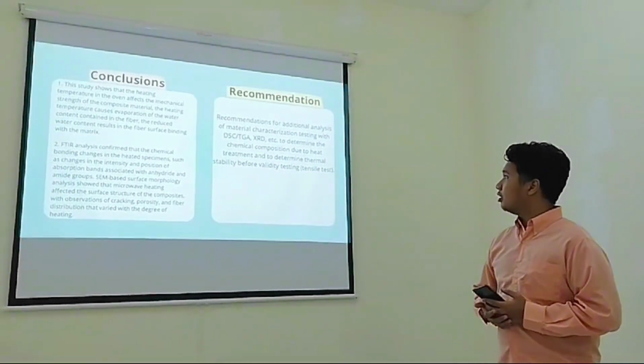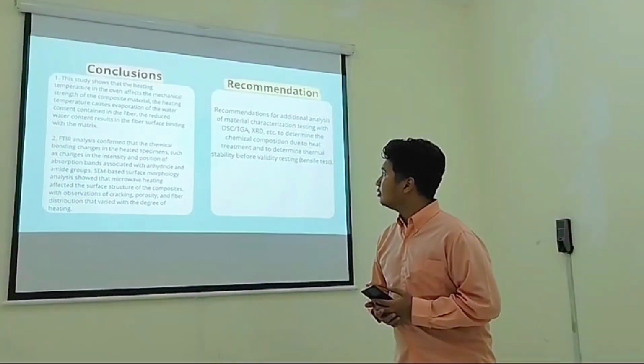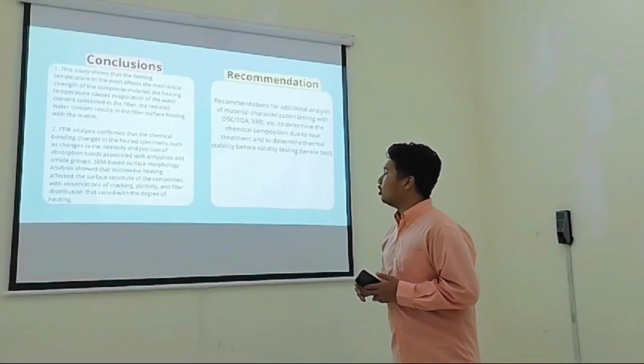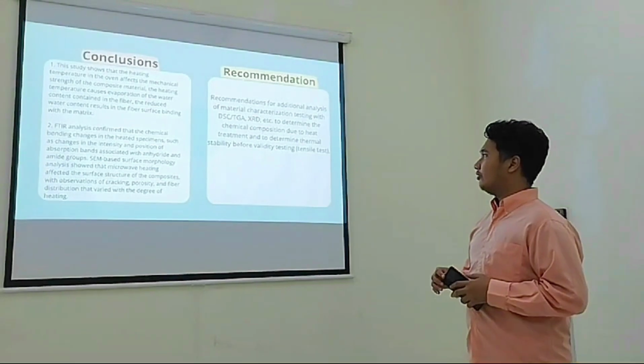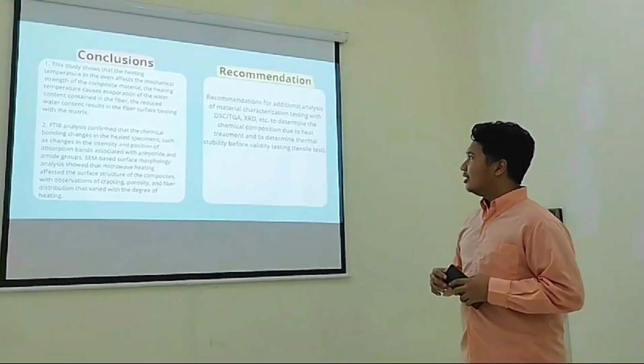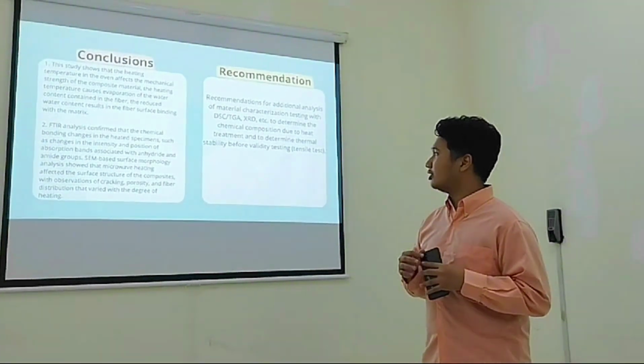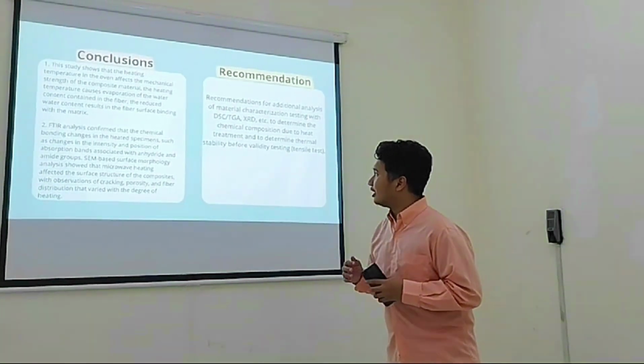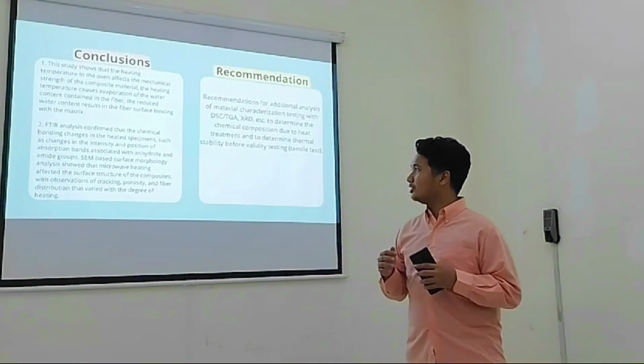Okay, next. The conclusion is that this study showed that the heating temperature in the oven affects the mechanical strength of the composite material. The heating temperature causes evaporation of the water content in the fiber. The reduced water content results in better fiber surface bonding with the matrix.